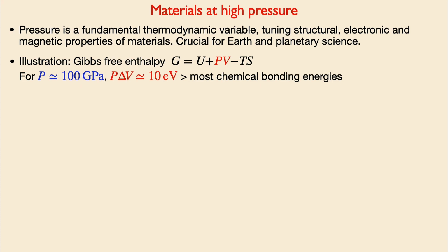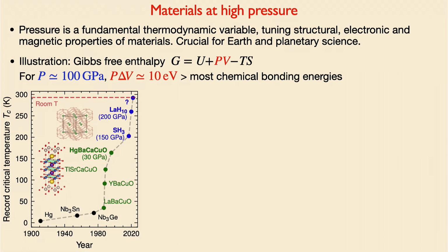Superconductivity was discovered by Kamerlingh Onnes in 1911, at the beginning of the 20th century. Then there was a very slow increase of the critical temperatures of materials. An important step in understanding the properties of materials was BCS theory, which explains superconductivity by the binding of electrons into Cooper pairs. BCS theory tells you that, taking into account Fermi levels and densities of states, there is a kind of limit around 20 to 30 Kelvin. And that was actually what was reached. All the compounds known until 1986 were limited to about 30 Kelvin for the critical temperature.